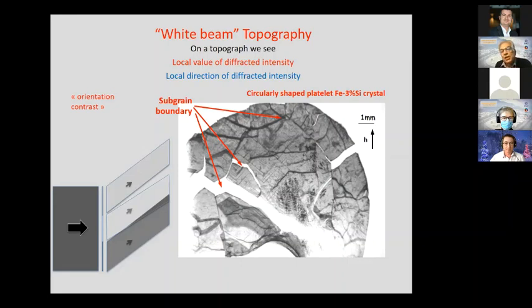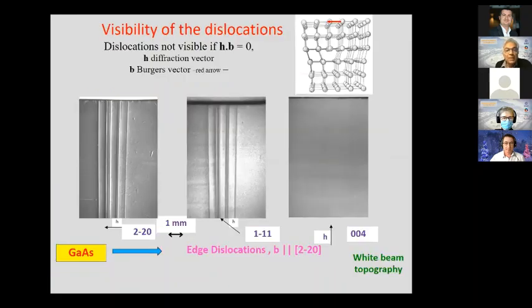So this is orientation contrast, and from that you can calculate the misorientation between the subgrains. On the other hand, when you do white beam topography, you record a lot of spots at the same time, and on some of the spots you see the dislocations, and on others you don't see them. And that is because the dislocations distort the lattice, but not in a uniform way.